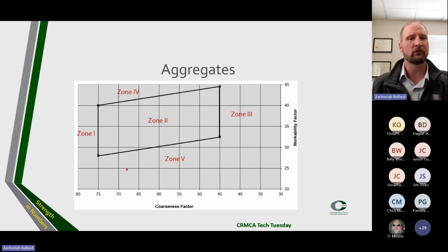Our zone 1 is supposed to be kind of our gap graded, very little amounts of intermediate aggregates. Our zone 2 is supposed to be our well graded aggregates in kind of what he called an optimal gradation for concrete mixture design. Zone 3's got a large majority of intermediate with a very little coarse aggregate. The zones 4 and 5 correlate to the extreme sandiness and rockiness ends of aggregate gradations.